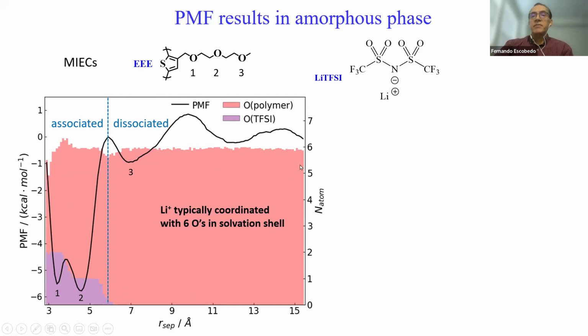But what's shown on this other scale on the right and with the colors is basically the kind of atom that's being associated with the lithium. So I said it's a 6 typically, and that's what you see at this upper bound. You can see that it goes up to 6. So that's basically all the oxygens that are coordinated with it. But you can see here in this sort of purple color down here that there will be the association of oxygens not with the oxygens in the PO, but the oxygens in the anion.